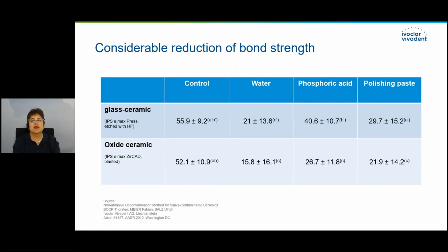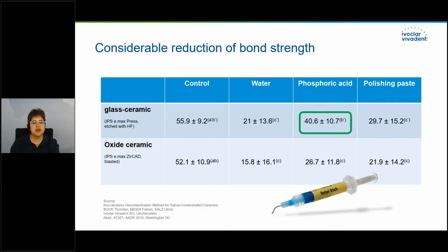Regarding the cleaning process after the try-in, depending on which material you are using for your restoration, the cleaning agent may interfere with the bond strength, whether it is lithium disilicate or zirconia. If you are using lithium disilicate, you can use, let's say, phosphoric acid, and it will not interfere with the bond strength. This is a good option. However, if you use it on zirconia, we will have a problem. Phosphoric acid on zirconia reduces the bond strength by half, from 52 to 26.